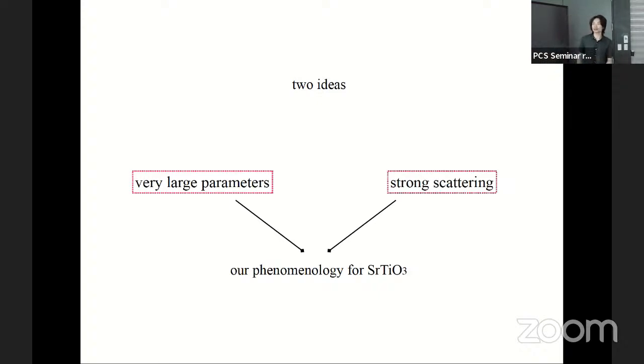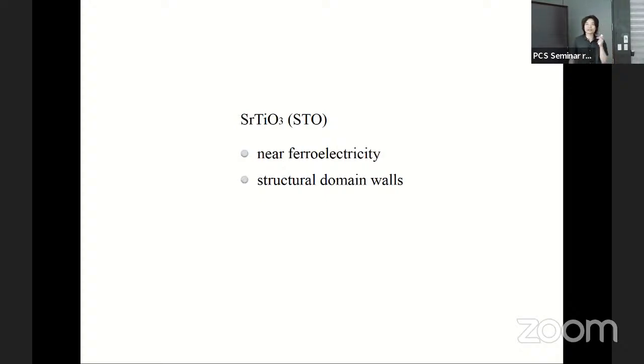So let's also use the other idea of strong scattering. And it turns out that STO indeed has this material property that allows the possibility of strong scattering. And it's because STO at low temperature has structural domain walls.